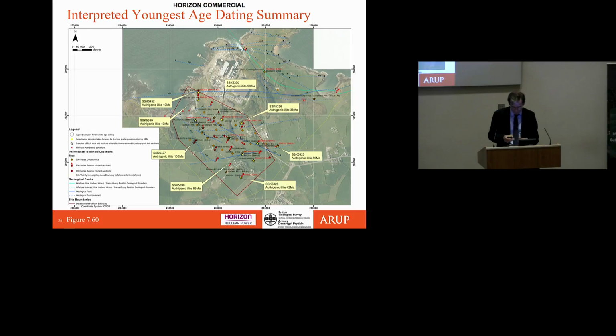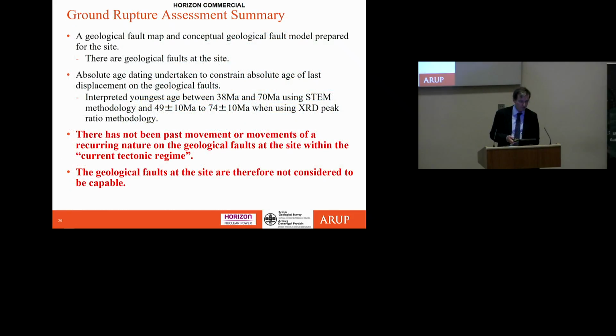So the very important conclusion that you can make from this, that we've done the geological fault map, there are geological faults at the site, we've done the absolute age dating, which is to constrain the absolute age of the last displacement on these geological faults that are at the site, and what we find is that the ages that we're restricted to, there's nothing younger than 38 million years, okay? And when we repeat that with the XRD peak ratio method, just a different method of interpreting the results, we got 49 plus or minus 10 million years, so the minus part would get you down to 39 or so. And you can see the upper end, 70 million years versus 74, also very accurate.